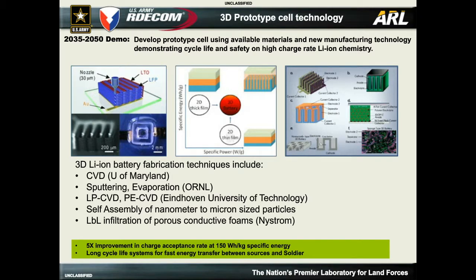So right now, most batteries, or all batteries, are made using slurry coating techniques. And the problem with that, of course, is that you have electrode porosity and you have macroscopic distances between your anode and cathode. And when you look at any of these, what people would call 3D batteries, what they really are is batteries that have very short diffusion lengths for, in this case, lithium ion. So when we look at that, we see that most of the technologies that are out there that produce 3D batteries aren't really scalable to large kilogram type batteries, which the Army uses. So a new manufacturing technology needs to be developed.